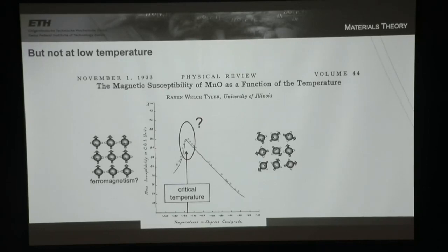This cusp in the magnetic susceptibility would have been very unexpected, because a cusp in a susceptibility tells you you've got a phase transition, and the thing that's ordering is the property that's associated with the susceptibility you're measuring. So in this case, we're measuring magnetic susceptibility. This is telling us that we have a magnetic order at some critical temperature. But the only kind of magnetic order that was known at the time was ferromagnetism. And manganese oxide was, of course, not a ferromagnet. So this was a discovery of a hidden order. There's some peak in susceptibility, but it's not amenable to being measured by techniques that were available at the time. And so that's what I'm going to mean when I say hidden order. It's not particularly exotic necessarily. It's some evidence for order in some measurement or some calculation, but there's no way of actually directly detecting it. So it's still hidden.